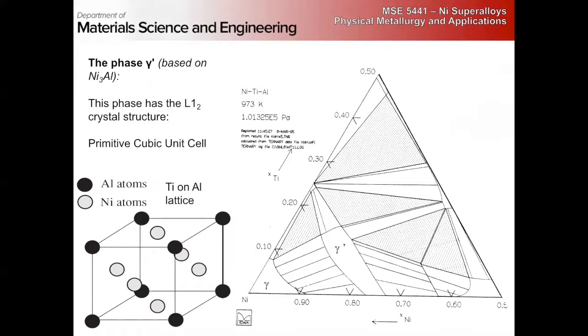But remember, a crystal structure is a lattice and a motif, right? In this case, the motif is an aluminum with three nickels, and this is periodically repeated at every one of the corners. So it's a primitive cubic lattice with a four atom motif, right? And if we look here, this is the nickel titanium aluminum ternary. I still hate reading these things, but you can still see here's the gamma and the gamma prime phase, and this is the region that we're playing with for the two-phase structure.